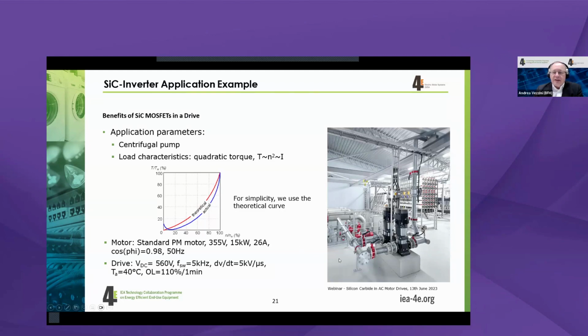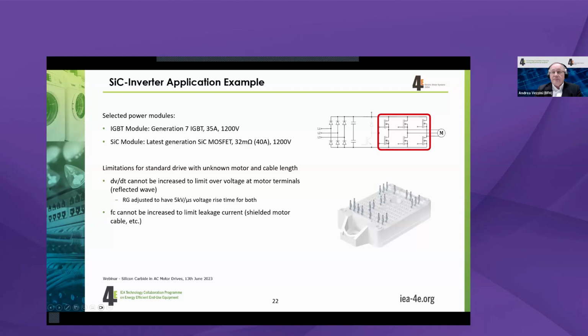Now, what's the advantage? We'll see this in the following example. A typical application is a pump, where you have a quadratic torque curve over speed. This is roughly a 15 kilowatt application, and we want to use a drive which has a switching frequency of 5 kilohertz, where the voltage switching speed is limited to 5 kilovolts per microsecond. This is a typical silicon-based drive. And we are going to replace the output drive with a silicon carbide MOSFET, where we have the following limitations. We keep the switching speed the same, so 5 kilovolts per microsecond. I will show later on what that means.